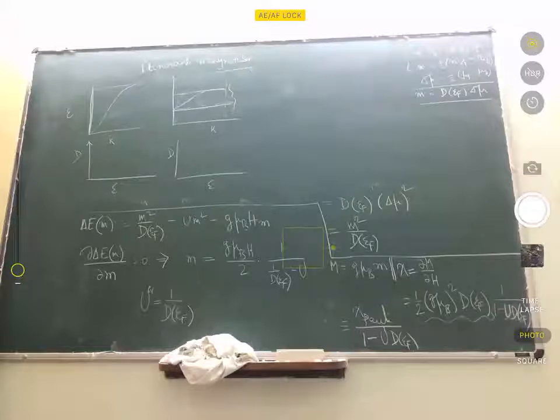Then the right one. So if you have the same number of states over a smaller energy range, of course, you have to have larger density of states. And the extreme case would be when you have a completely flat band. Then the density of states would sort of be a delta function. So now if you have such sharp density of states or peaks in density of states near the Fermi energy or at the Fermi energy, then this theory tells you that that system would be unstable and it would prefer to go to a ferromagnetic state, would sort of develop moments which would lower its energy. In fact, that's how you explain ferromagnetism through this.